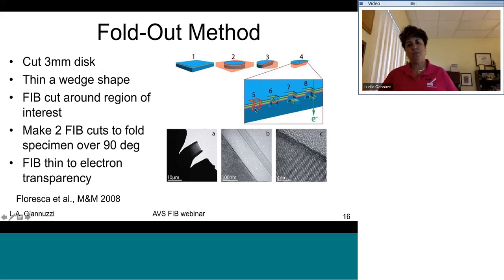And then the FIB was used to cut perpendicular to this, so we cut 2 lines so that the sample fell over, and then continued to FIB mill in this direction so that you can put the electron beam through the thin area there. And you can see it. Again, these are ways to make the sample or FIB mill samples without lift-out.